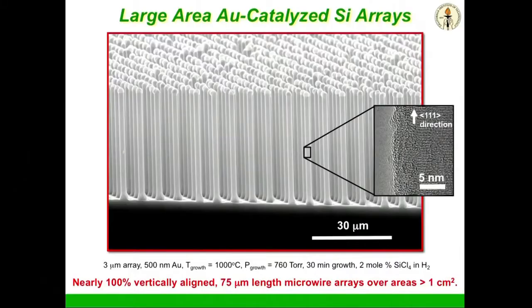This is really crappy silicon. Its diffusion length is only a micron because it's impure. It's saturated with gold or copper. You would never use this in a photovoltaic cell device because the first 1 micron would be live and the other 199 microns would be dead. But in fact, in this case, they absorb all the light with 200 microns, but everything is within a micron of being collected. And so when we infiltrate this with a liquid, we can collect all those carriers in material that's much cheaper and much less pure than you would ever tolerate in a standard planar photovoltaic system.